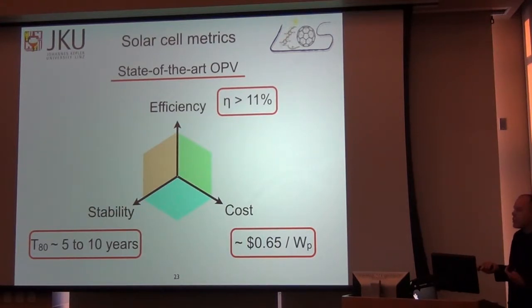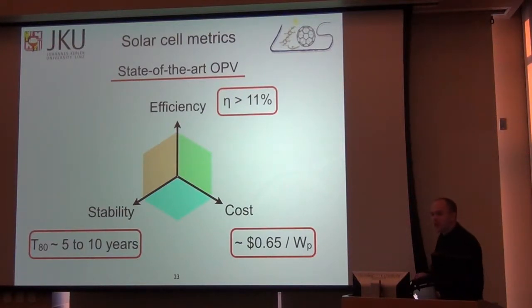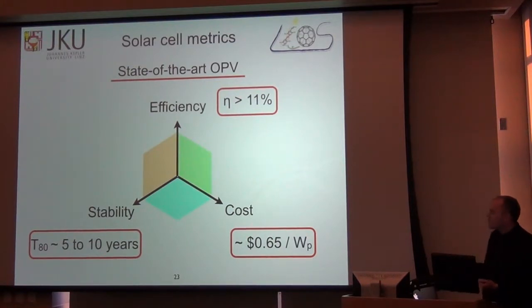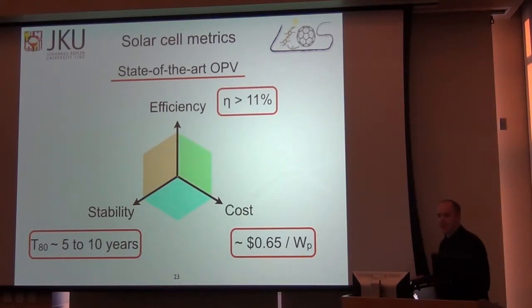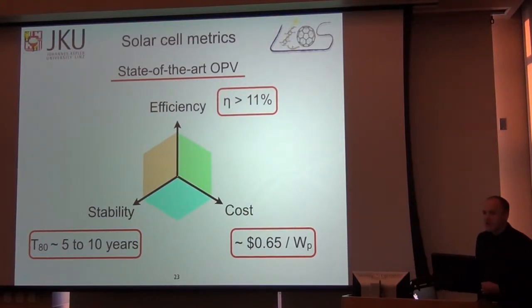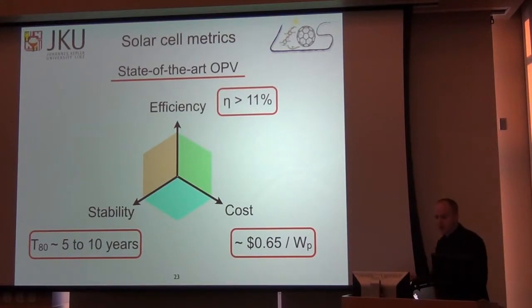And once we have an efficiency, we're concerned with what the device stability is, how long it will last, and how much it costs. A reasonable cost estimate for organic solar cell devices, assuming certain parameters for scale-up, is on the order of 65 cents per watt peak. And the stability estimate of commercially available modules now is on the order of 5 to 10 years, but they were not really made 10 years ago, so we have to kind of extrapolate what their degradation lifetime might be into the future. That's just where we stand now.